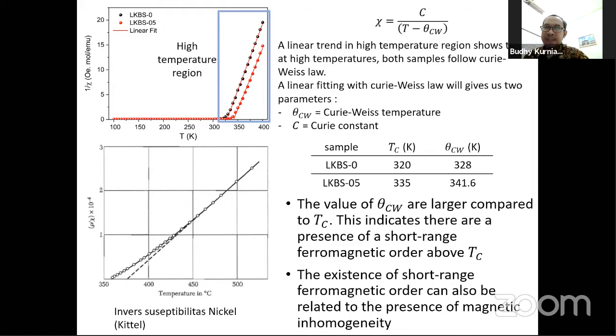So what is the meaning of this condition? This indicates there is a presence of short range ferromagnetic order above the TC. The existence of short range ferromagnetic order can also be related to the presence of magnetic inhomogeneity. It means there is a mix of paramagnetic and still ferromagnetic order. Next, please.